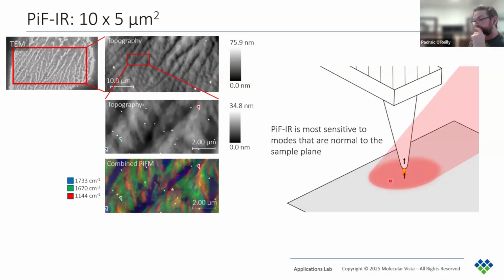So what we've found is, it's going to depend on your scan size, and it will depend on your pixel density, so the resolution that you use for it. If you're not super interested in the fine details of the structure of the particle, you can use a lower resolution pixel density, so you can scan faster. In the examples I show, I say 1 to 2 minutes per defect is what we found using our automated defect review. And that mostly comes down to whether we use, let's say, a 64 by 64 pixel density or a 256 by 256.